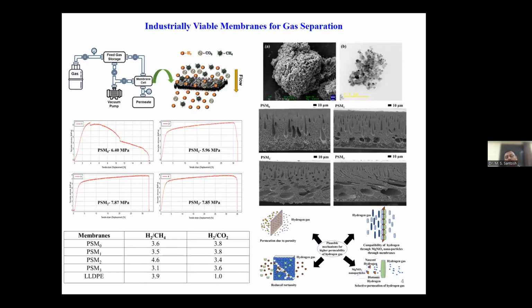As you know, magnesium and nickel both have good affinity towards hydrogen, and hence, because of the presence of these highly effective magnesium and nickel atoms associated with this nanoparticle, they probably may enable the separation of hydrogen through the membrane in an effective manner.